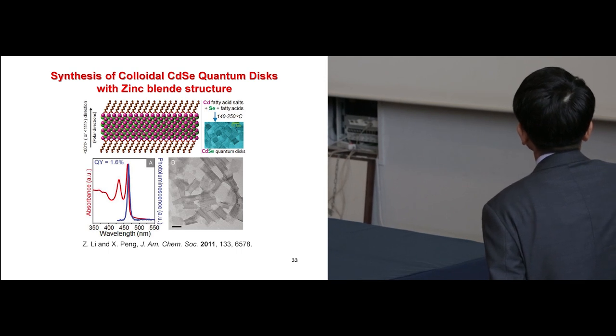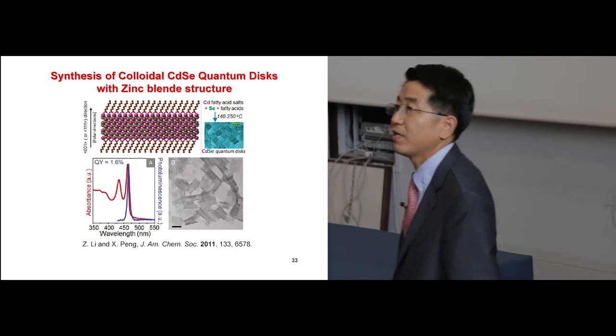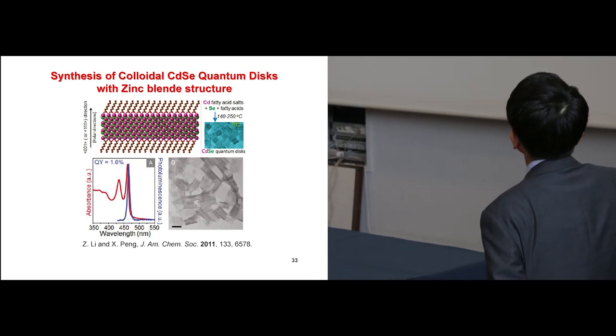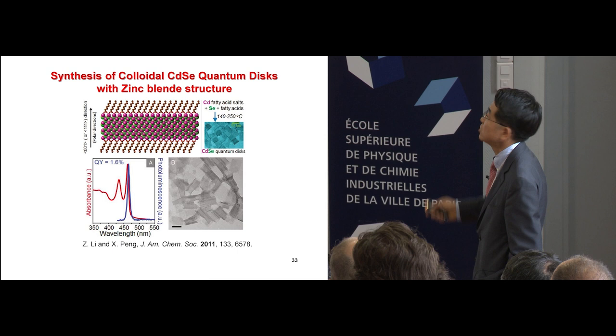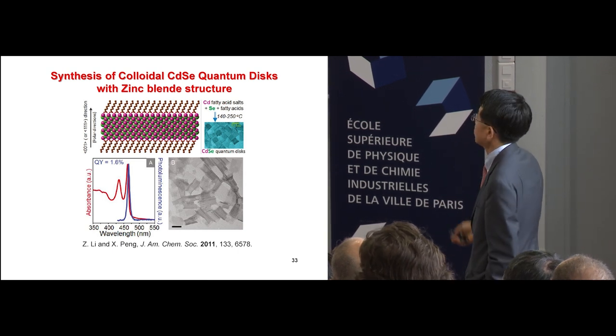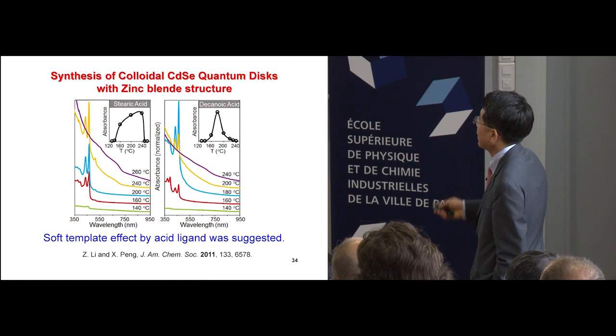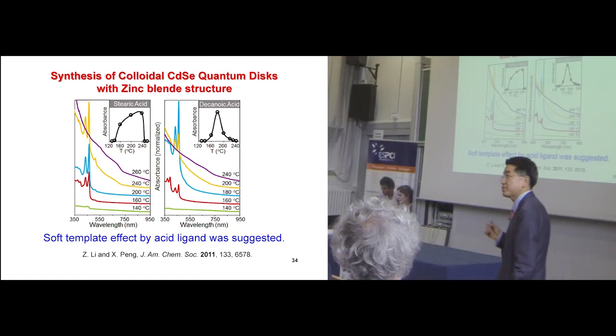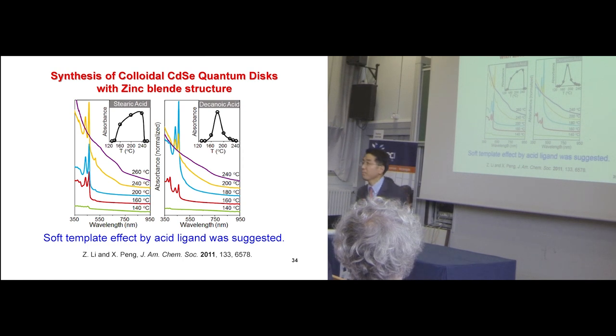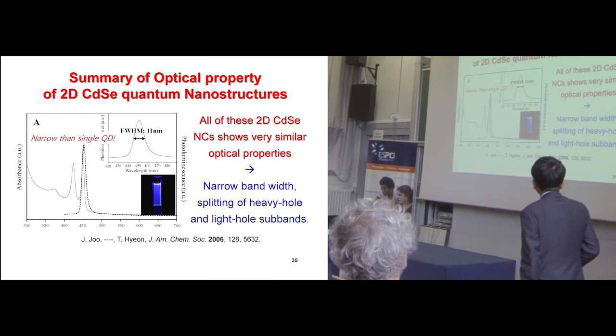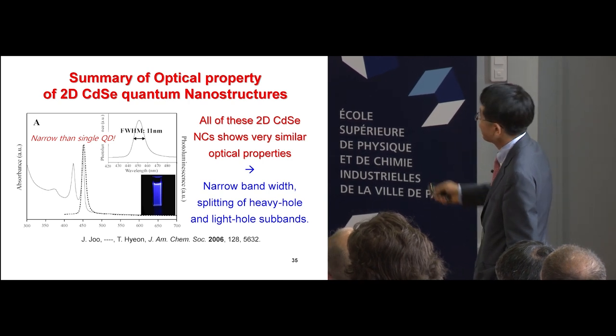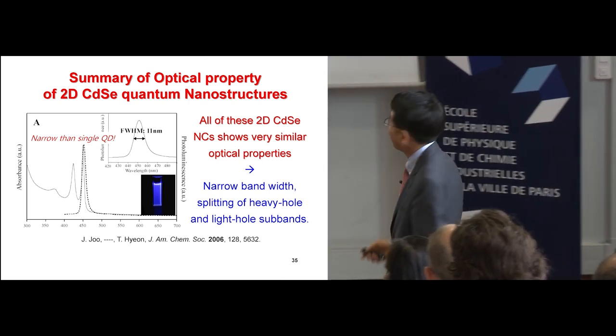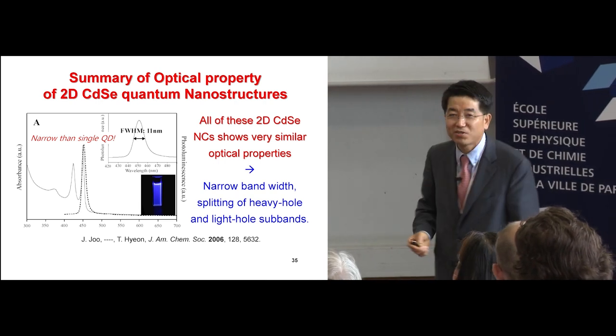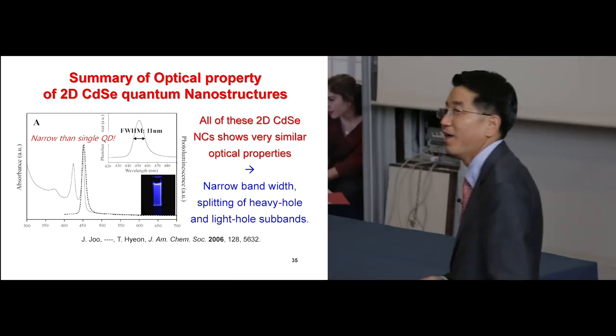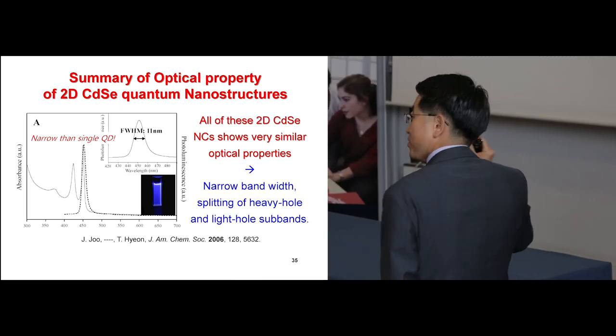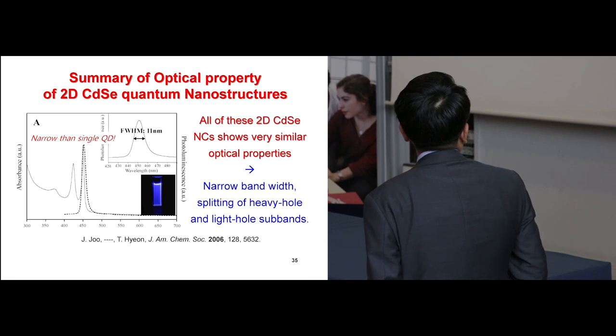Basically, what he said was that the surfactant plays some kind of templating role, and could make the zinc blende structures in CdSe quantum disk or ribbon structures like this. They showed that this surfactant can be used as a soft templating material here. As a summary, this is what I showed you earlier. One of the interesting parts of this material is that it gives a very sharp PL, as I mentioned earlier, very sharp PL in the blue region.